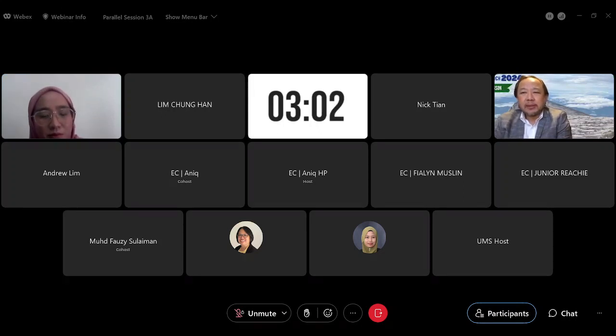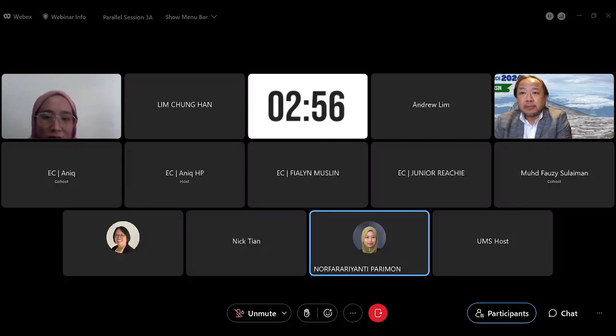Okay. Thank you, Amira. Any questions? Maybe I can answer for Amira's question. Actually, the sample is annealed at 500 degrees C. The experiment is at room temperature, but the sample itself is annealed or calcined at 500 degrees C. But the problem is the sample is deposited or grown on glass substrates. So the melting point of the glass substrate is maybe around 550, so we can't anneal higher than 500 because the glass substrate may crack.